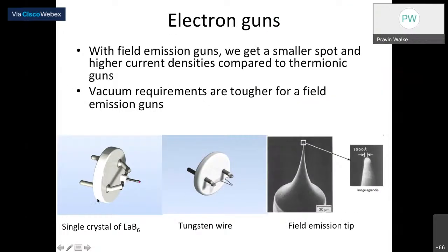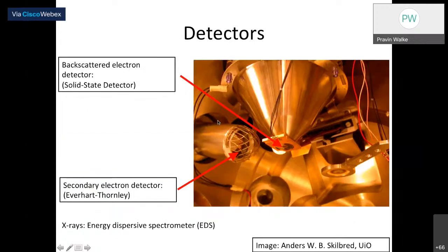And here are some pictures just for your understanding. It is very difficult for us to go and see inside the system how those beam guns look. But here you can easily see in the picture the single crystal of LaB6. Then here you see the tungsten wire, which is connected between two points, and a very high voltage is applied across these two, and electrons get generated from this. And in the FEG gun, the field emission tip, a tungsten tip, has a diameter of around 1,000 angstrom, right? So this will emit high current density electrons, right? So these are the simple electron guns people are using.